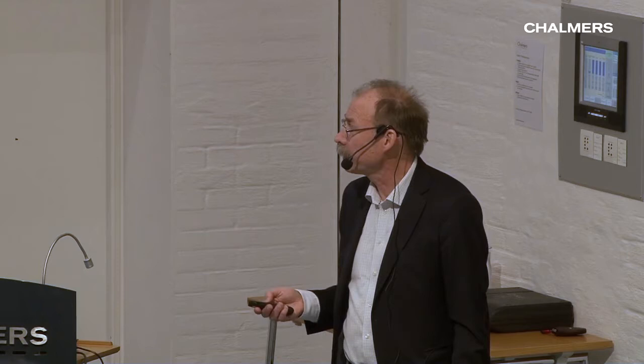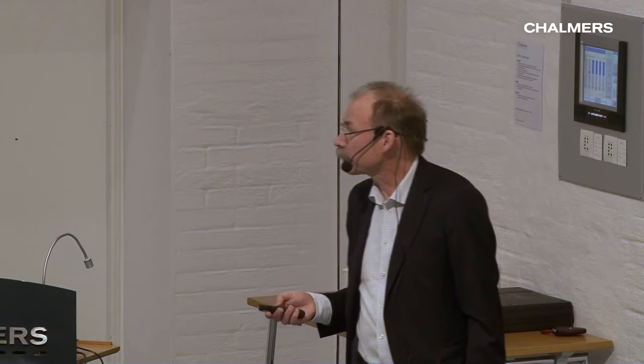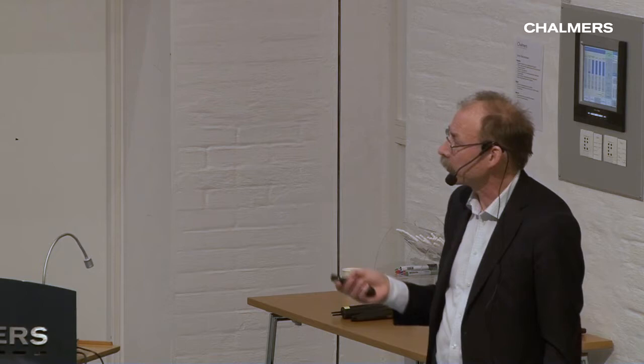One possible process looks like this, and I will not go through this. I will say a few words about the steam explosion in the beginning, very few words about the alkaline treatment, where we separate the cellulose and the lignin. We are at the moment working with that. I will say a few more words about the lignin, how we take care of the lignin in this process. And the interesting thing here is that if we compare with the kraft process, we have replaced two quite expensive process units, evaporation and the recovery boiler, with the lignin conversion unit.